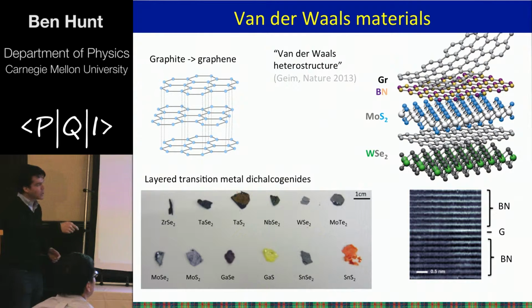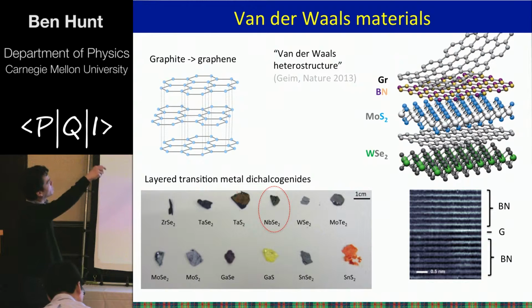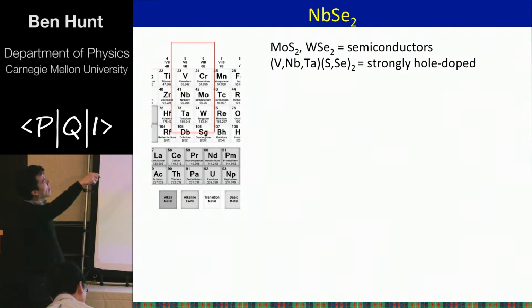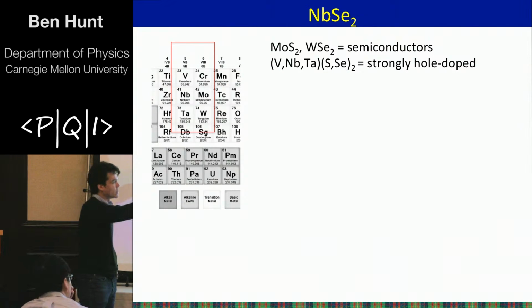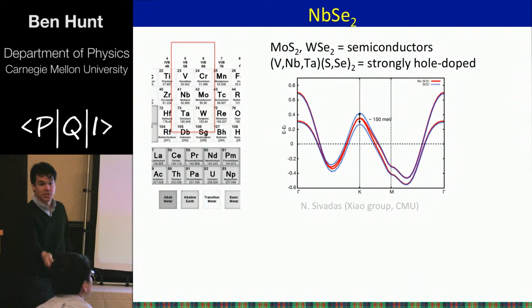Okay? So the subject of the talk today is this one, which is a classic superconductor, niobium diselenide. Okay? So if you've heard of these transition metal dichalcogenides at all, you've probably heard of molybdenum disulfide or tungsten diselenide, which are the semiconductors. But if you go one column over in the periodic table and you take away one of the d electrons in the system, what you end up with is a system that's highly hole-doped, right? So here's a calculation of the electronic bands. I'm missing all the references here. I think I chose a bad color. But this is from Di Xiao's group, actually from one of his students that calculated the electronic bands. And here you can see the Fermi level intersects a couple of different pockets of the Brillouin zone.